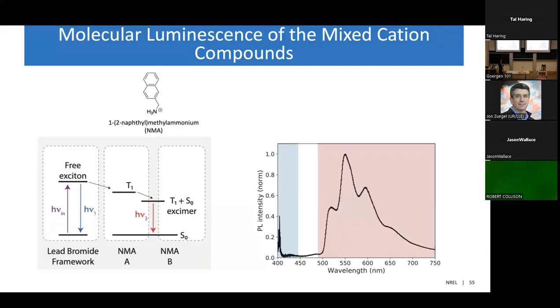For the pure naphthalene lead bromide perovskite, we see something familiar. So this looks like what I showed in the previous study. There's very little emission from the inorganic exciton, and then most of the emission is coming from naphthalene triplet excimers.